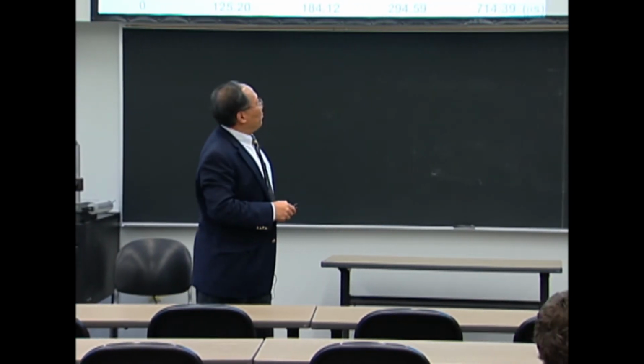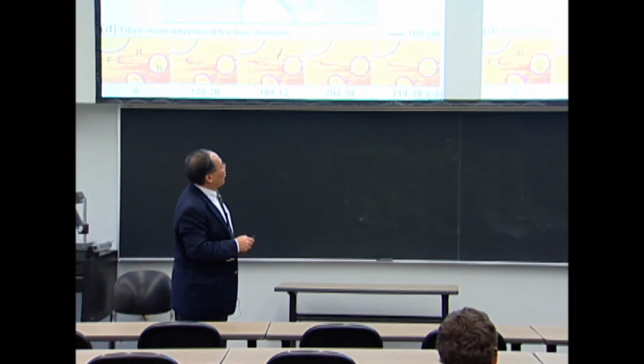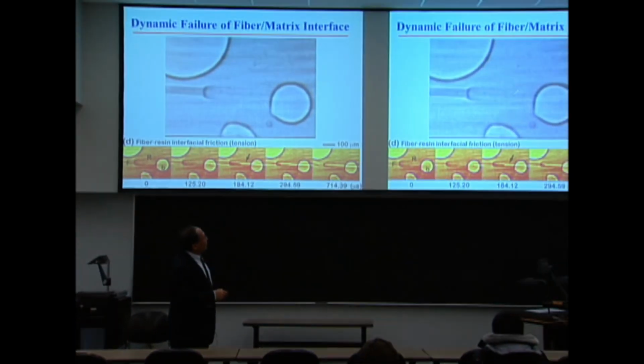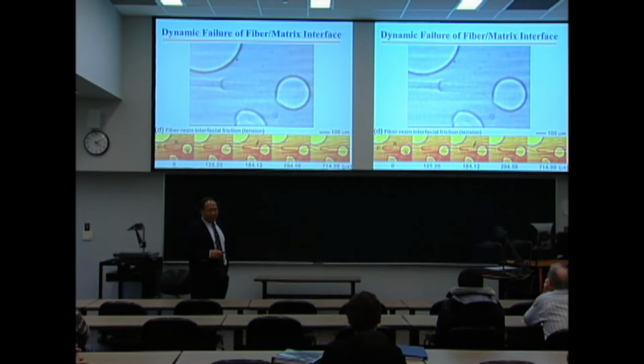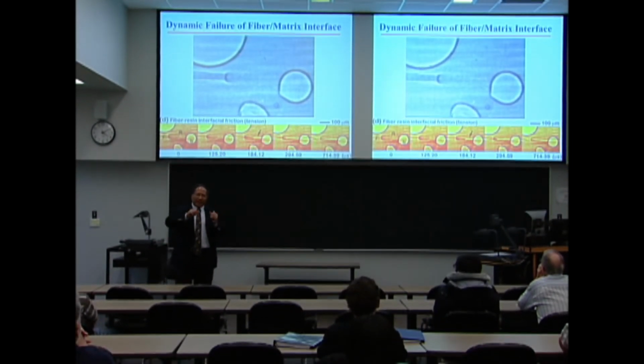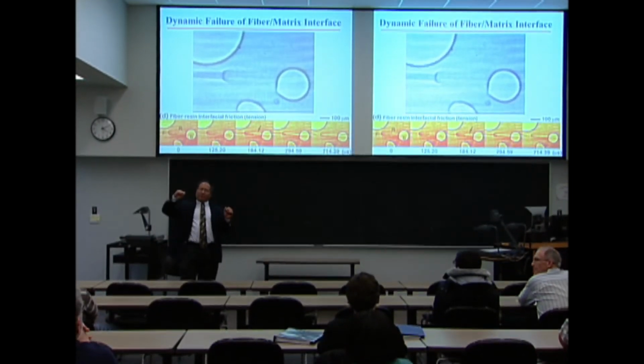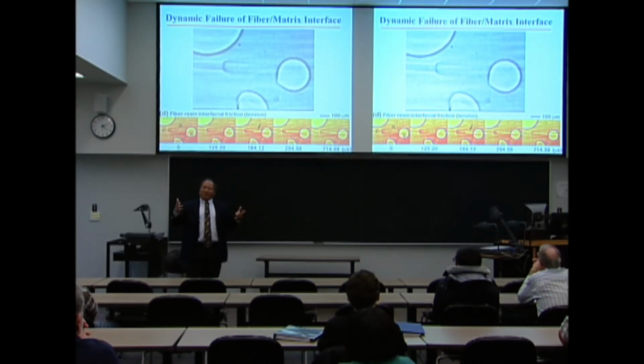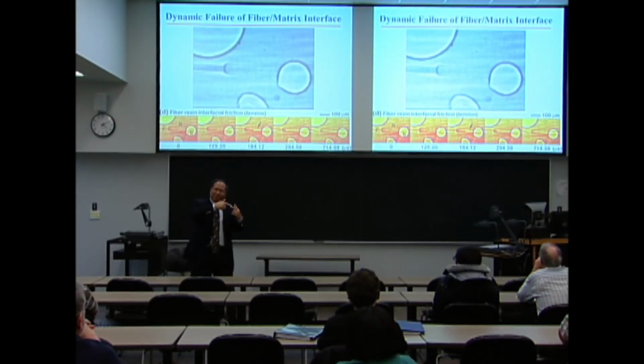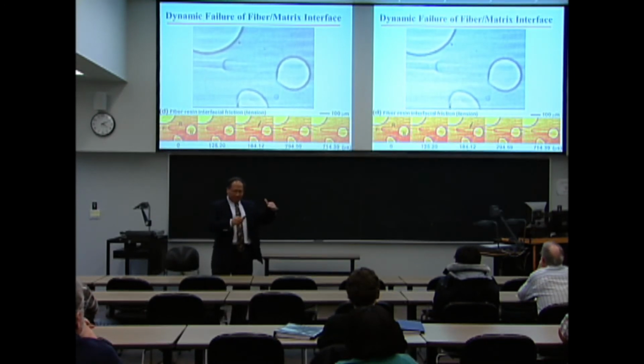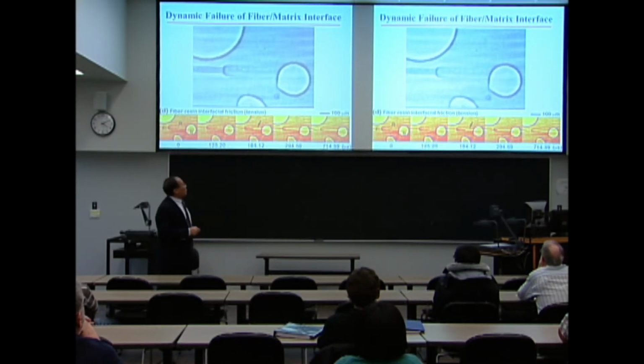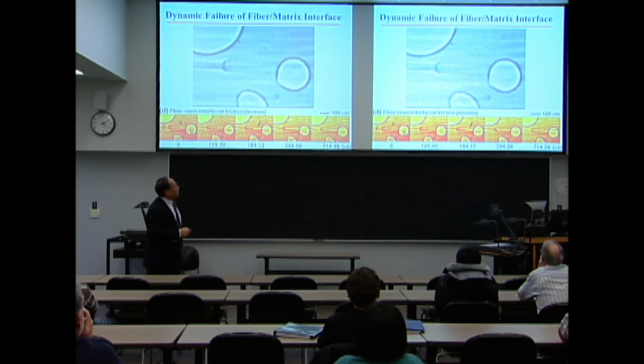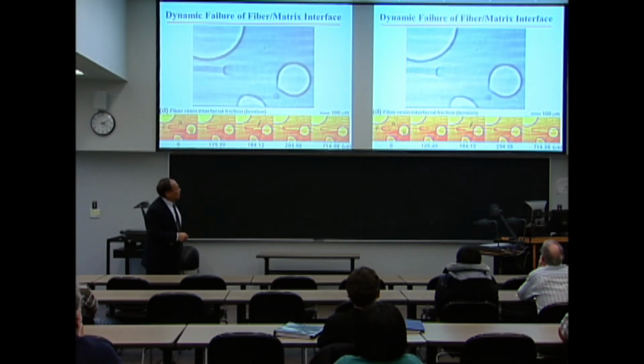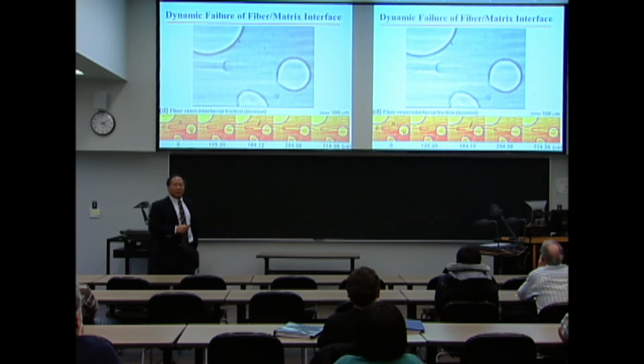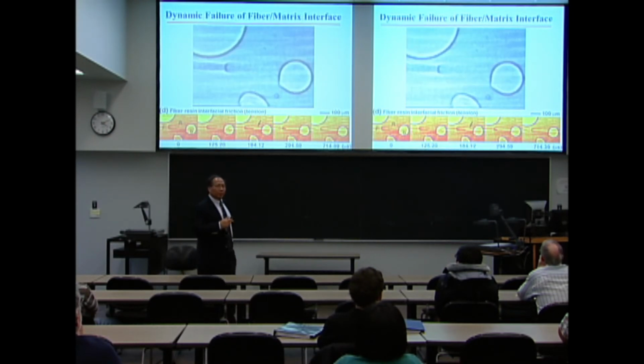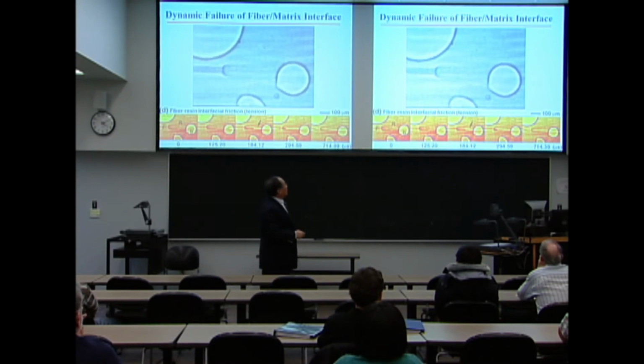This is an interesting experiment. We're pulling out a fiber. This is a 12-micron Kevlar fiber from the epoxy base. If you're in the composite field, many people are looking at how much force it takes to pull one fiber out of the composite material. Nobody has ever seen the interface, how the fiber actually gets pulled out from the matrix material. And this is the first time you can see how the interface forms. You can actually increase the contrast of the images, and we have the loading histories, so there is quite a bit of analysis you can do behind this.